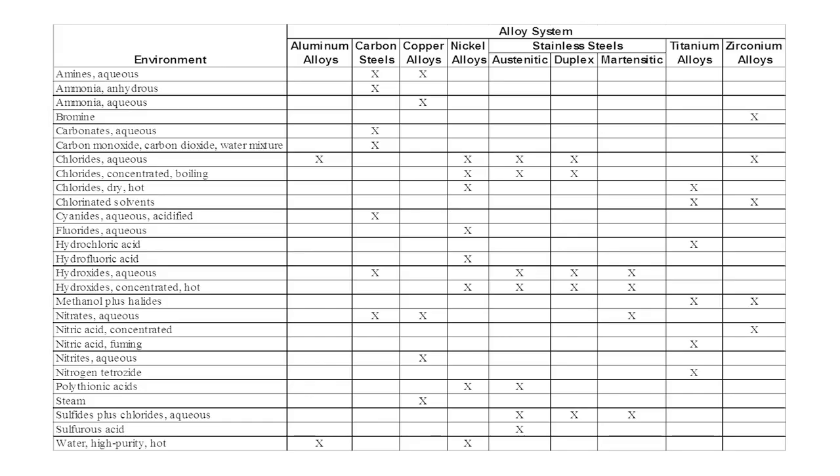Different metals are sensitive to cracking from different media. For example, stainless steels are sensitive to chloride environments, copper alloys are sensitive to ammonia environments, and higher strength steels are sensitive to hydrogen sulfide. SCC can be attributed to the combined action of three factors: tensile stresses in the material, a corrosive medium such as chloride-bearing or hydrogen sulfide media, and finally the selected material susceptibility to SCC.